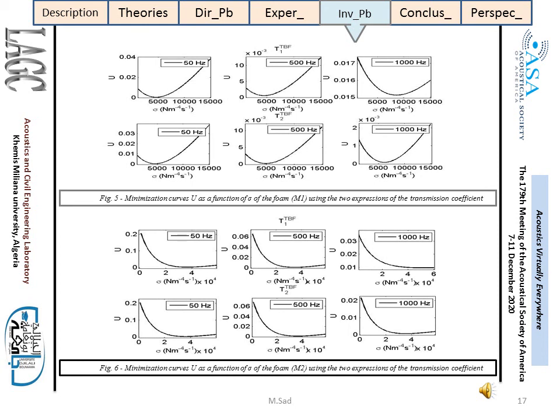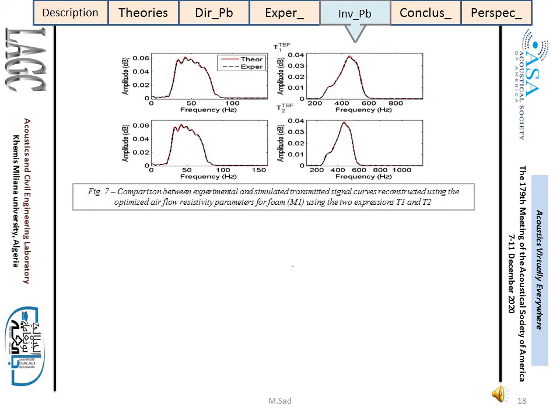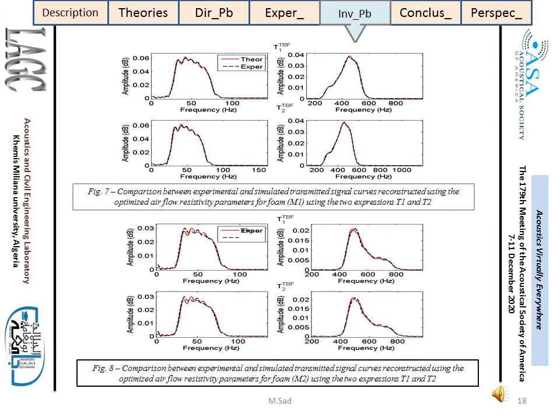Figures 5 and 6 give the minimization curve U as a function of sigma for the two foams M1 and M2. Figures 7 and 8 show the curves of the transmitted signals reconstructed using the optimized parameters of the flow resistivity with respect to the corresponding experimental signals. From these figures, a good agreement is observed between theory and experiments.